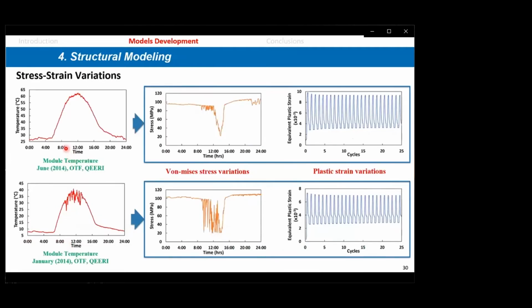Now we take one day in January and one day in June from Doha, from our outdoor testing facility, and we simulate the stresses during that day. This is the temperature in the panel, or in the PV cell, and this is the temperature for January in the PV cell. We looked at the same day and see how the stresses evolve. As you can see, you have some relaxation due to the fact that temperatures increase. From this, we repeat this same day 25 times, so this is a cyclic loading that we have, and we calculate the plastic strain.